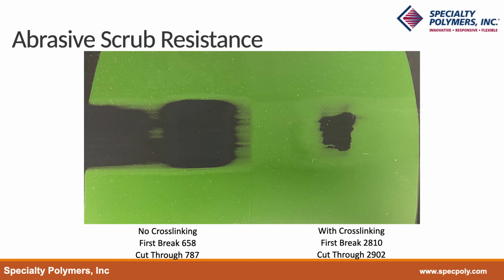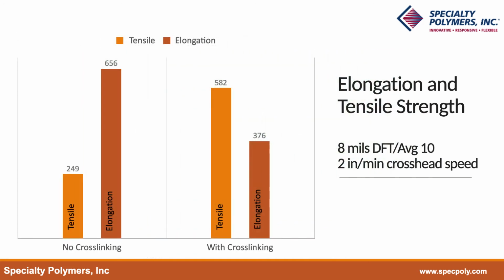We think that the improved abrasive scrub resistance is a result of the interpart. You can see the tougher film in the increased tensile strength of the cross-linked paint. It increased from 249 to 582 psi for the cross-linked paint. As you would expect, we got lower elongation when the tensile strength increased, but the elongation of the cross-linked paint was still very respectable at 376%.